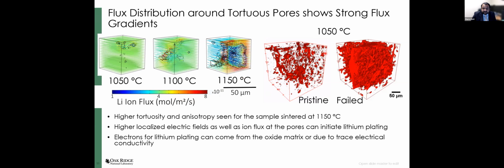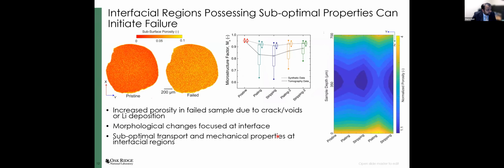And you can see that the bulk microstructure is more, quote-unquote, porous, where we have a higher X-ray transparent region that is consistent with the idea that filaments are forming within this solid electrolyte. We were also able to show a little bit of what the microstructure itself does. Because we are able to image an entire solid electrolyte, we are able to show that there are regions within the electrolyte that have very distinct microstructures internally. So we have regions with much different microstructure than the normal, and that leads to transport and mechanical properties that are very disparate, which causes these suboptimal regions that cause failure.